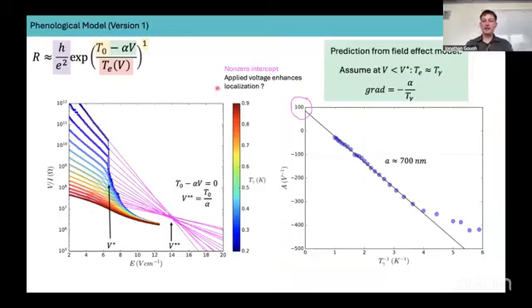We can compare our data with the field effect model. This was this linear voltage term here. One prediction is that the gradient of these curves, shown here, should be proportional to 1 over temperature. So the gradient is given by this value A, and this is 1 over temperature. And we see this very nice straight line, which is also encouraging, that this simple model can describe our data very well. The gradient of this curve actually provides information on the system, namely this typical hopping length, A.